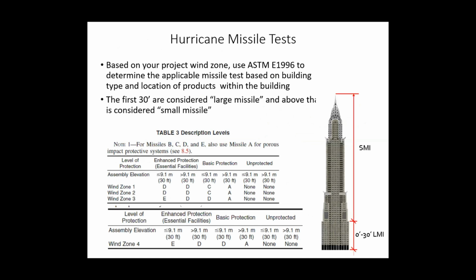So looking at this from ASTM, the first thing to note is that the first 30 feet of the building is where you have large missile requirements. That's mainly because a large missile like a 2x4 probably isn't going to fly higher than 30 feet. It may, but it may not. But lighter missiles like gravel, or anything that's lighter, may fly higher than 30 feet. So we call that small missile. So that's a little background on that.